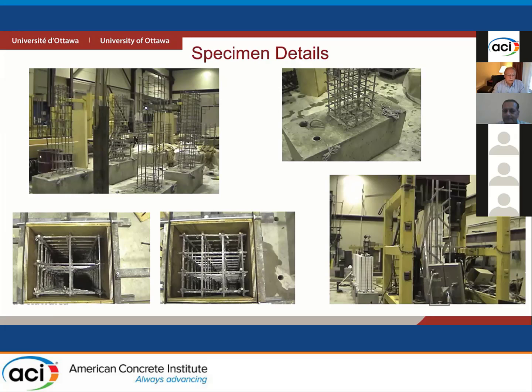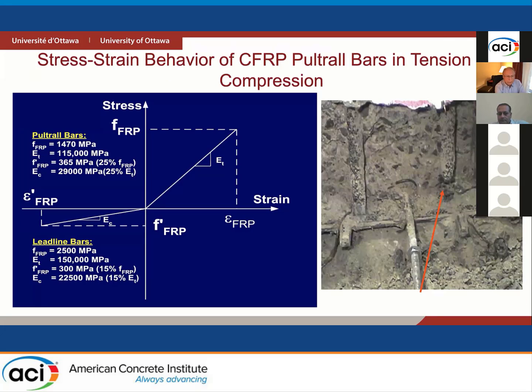Here you can see the construction stages of specimens with different shear spans and also cross-sectional dimensions. As you can see, we either had 8-bar arrangements or 12-bar arrangements using CFRP Pultrall bars, and then subjected them to constant axial compression and lateral load reversals. In terms of material behavior, we did a lot of coupon tests, and our coupon tests agreed with what was specified by the manufacturer, and we went up to approximately 1,500 megapascals of tensile strength. In the second phase, when we tested columns under monotonically increasing load, we used Japanese LeadLine bars, in which case we went up to 2,500 MPa.